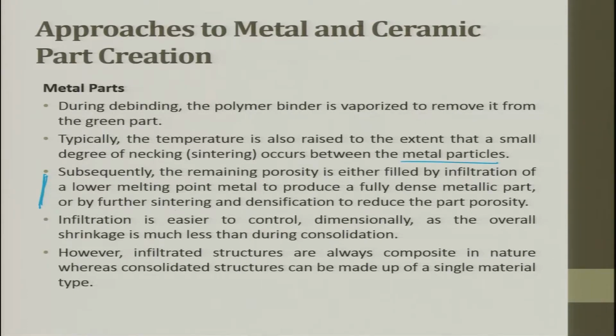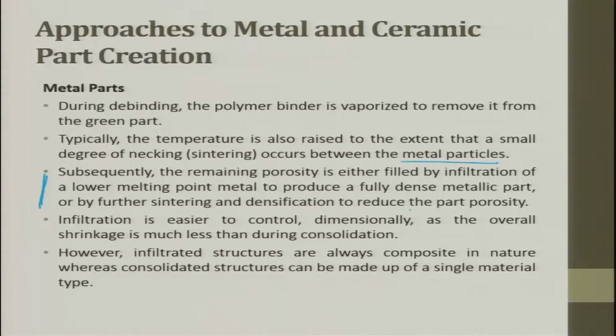Where is the application? You make ceramic porous material and then inside the ceramic, through the pores, you try to infiltrate metals. So, these metals which are infiltrated give you lubrication. Okay. So, there we use this application exhaustively. Infiltration is easier to control dimensionally as the overall shrinkage is much less than during consolidation. However, infiltrated structures are always composite in nature, whereas consolidated structures can be made by a single material type. Infiltrated structures are always composite in nature.